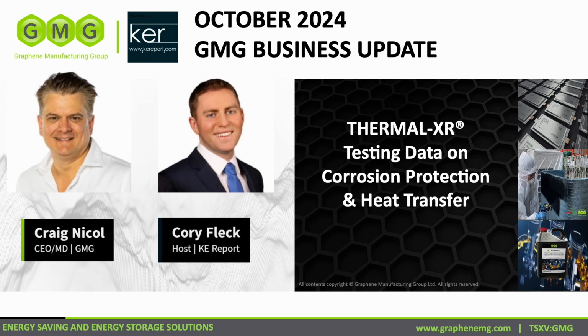So when it comes to the heat transfer data, yes, 2.2 times more efficient at heat transfer than bare aluminum, 8.6 times more efficient heat transfer with radiative heat. What are maybe the biggest markets that this impacts? Yeah, I think just straight out radiation heat transfer is your heat sinks. So for your phones, your laptops, your hard drives, there's heat sinks generally in there, and we can fundamentally change those with this coating. We can make that 8 times more heat transfer, and then we can wick that heat away. The product can last longer, perform better because the temperature is lower.